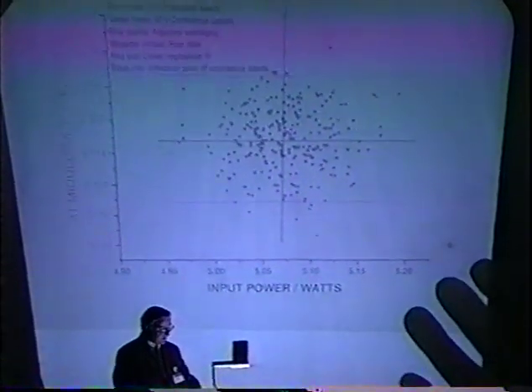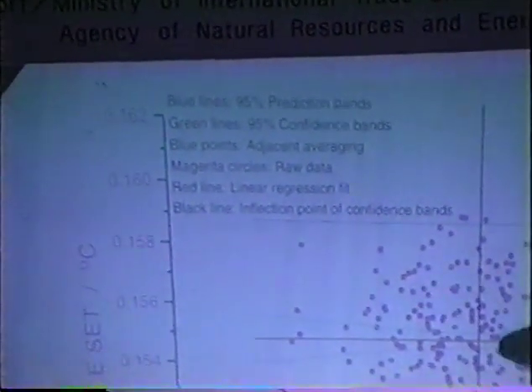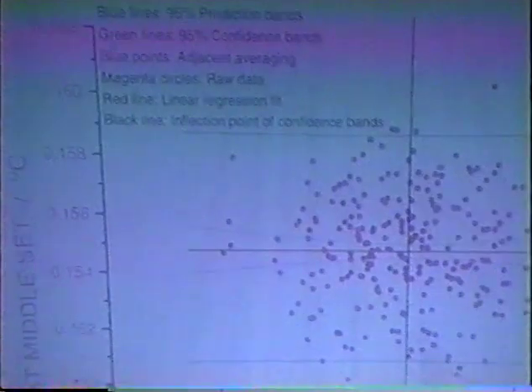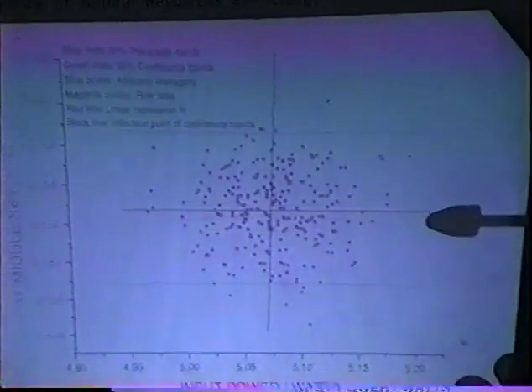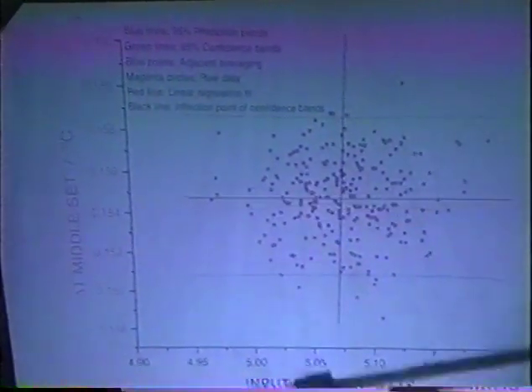You can then do statistics on that spread. You can determine the confidence limits and the prediction limits for that. You can look for the point of inflection of the confidence limit curves, which gives you a good estimate of the actual power, the average power, and the straight line fitting through the points gives you a good estimate of the middle set of the temperature. You have to do that for each one of the sets of thermistors.